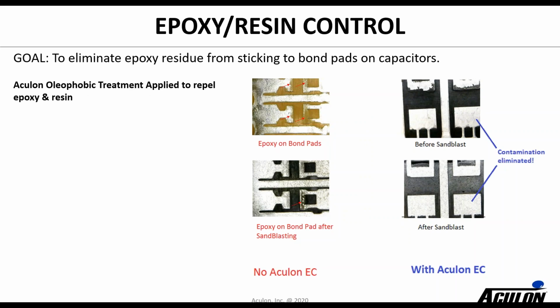Another area which is interesting, very specific in electronics, is controlling epoxy and resin. Sometimes you want to stop the epoxy residue from sticking to bond pads on capacitors. Here's an example on the left-hand side where you can see, without Aculon epoxy control, in the top photograph, you've got some epoxy on the bond pads. They use sandblasting to remove that, but you can still see there's some epoxy still on the bond pads below. Well, if you treat these capacitors with the Aculon epoxy control, you can see before the sandblasting the epoxy's on it, and afterwards that surface is clean. So that allows you to achieve your goals of increasing your yield and better throughput as well. So that's an example of keeping epoxy away.